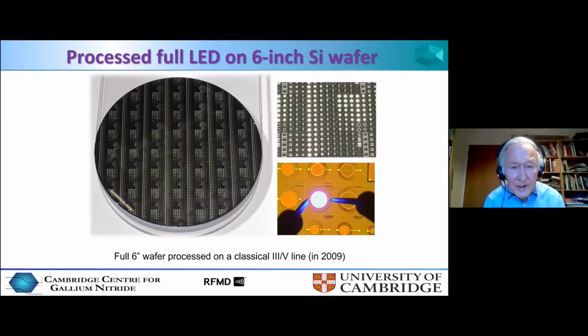And this photograph is an image of the first processed 6-inch gallium nitride LEDs, and it's processed by industry called RFMD, and that was done in 2009, and that was the first time in the world it was done. And in fact, the pattern you see on this wafer are test structures of LEDs of different sizes. And then the top right-hand side is a magnified image of part of this wafer, and then the bottom right, we're just passing a tiny current through one of these LEDs, and it's brightly shining. And in fact, it's emitting blue light, but it's so intense, it's saturating the detector, and so it looks like white light. So this was a great success story. As I say, it was all being funded by EPSRC.